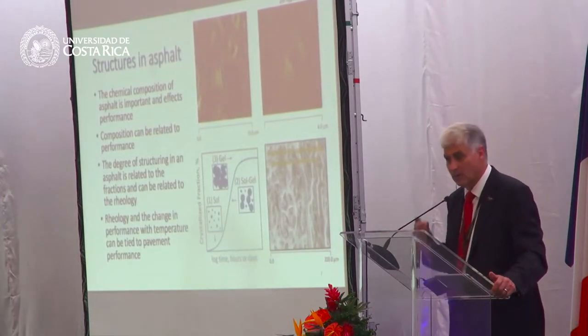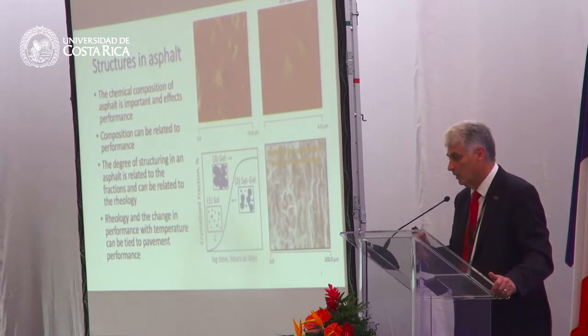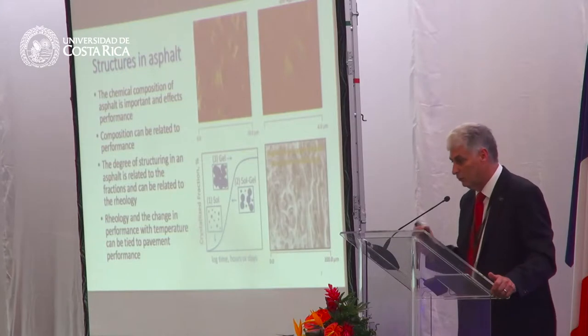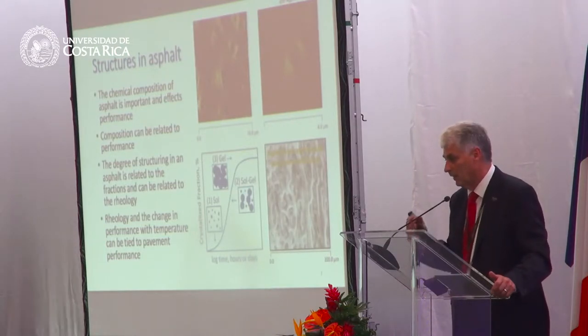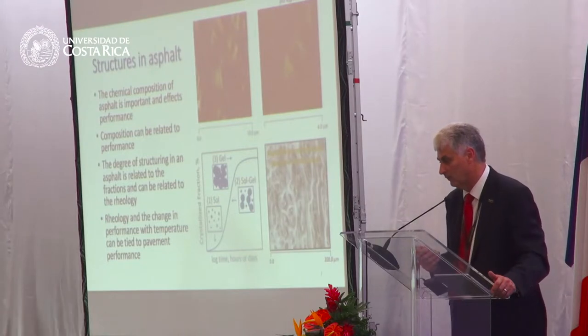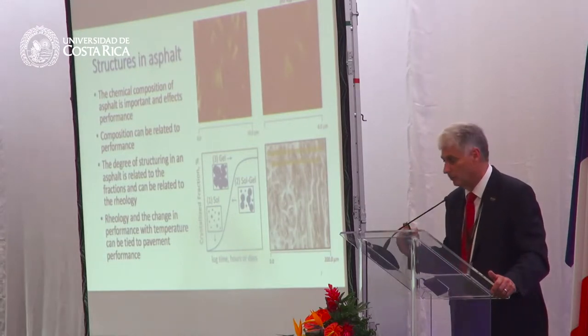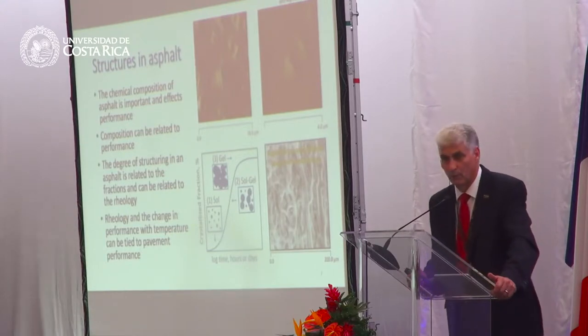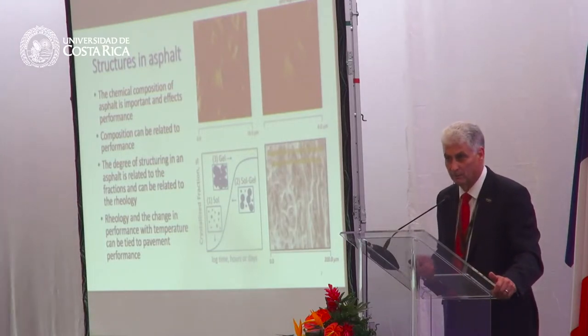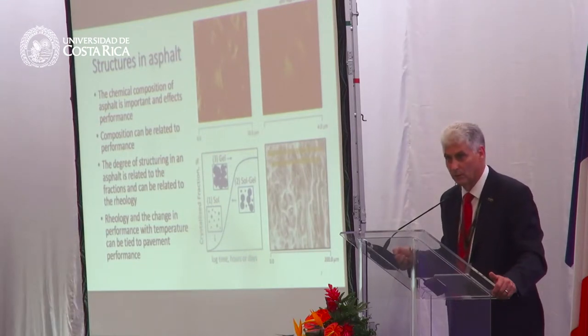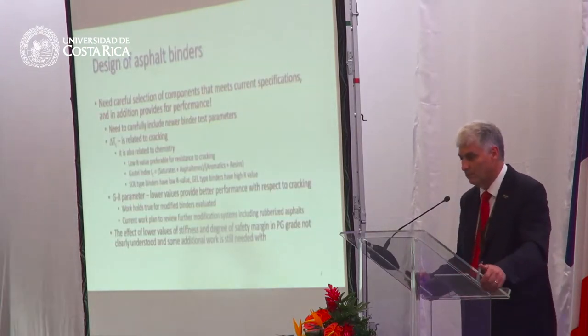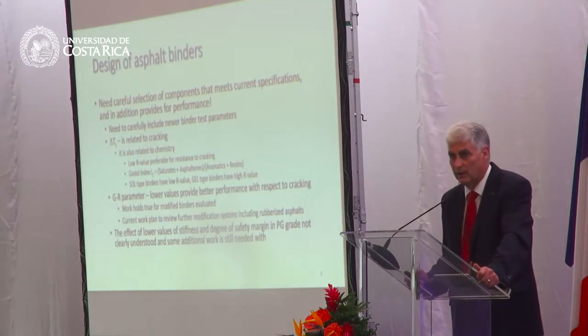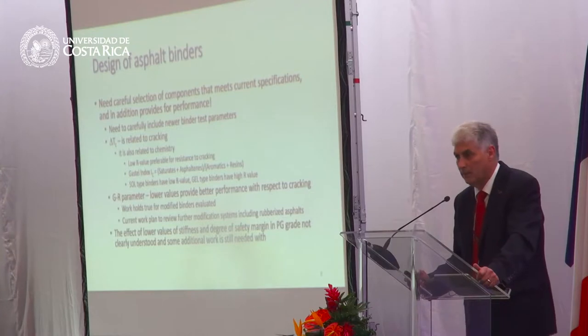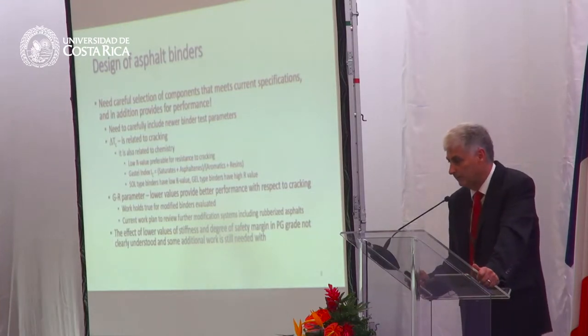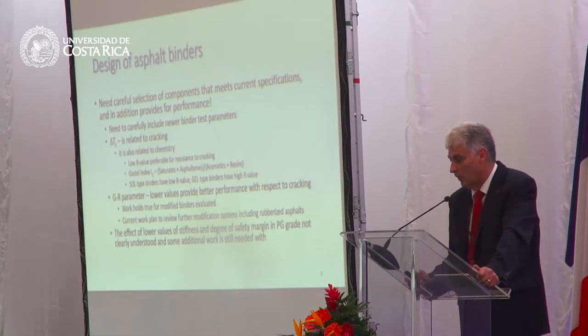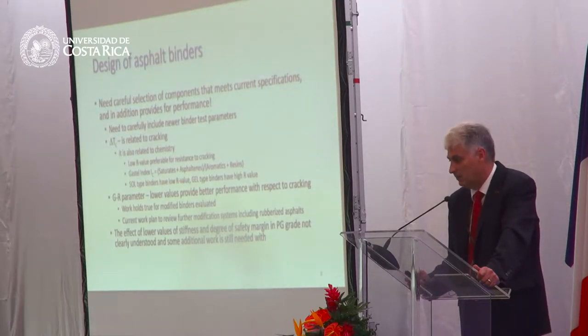Now, the important thing is that we know that the chemical composition can be related to performance. The degree of the structuring that you see in the asphalt is significantly related to the performance of those asphalt fractions. Now, what we need to be able to do is to tie that rheology with changes in performance to temperature and then on to pavement performance. So this is one of the goals in terms of our understanding. When we design our asphalt binders, we need to have very careful selections of the components that meet the current specification parameters. That being said, we need to carefully include newer binder test parameters.